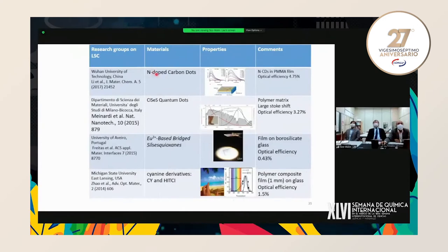Here, the quantum dots were fabricated by a Chinese group from Wuhan University of Technology. They fabricated nitrogen doped carbon quantum dots, and their efficiency is quite high compared to other reported quantum dots, around 4.75. However, their absorption and emission lie in the visible region, so maybe it will not give transparency in the material. Another is copper indium selenide sulfide quantum dots, from the Italian group again. They fabricated some semi-transparent LSCs. It has quite good efficiency compared to the other lead and cadmium-based quantum dots, around 3.27.